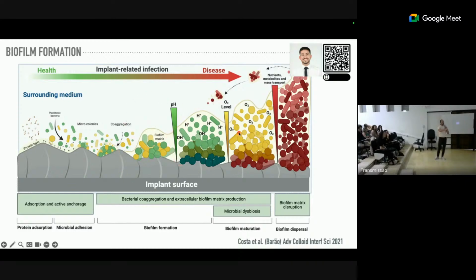In the beginning, this biofilm is more acidic, as we call it. So the pH in the biofilm tends to be low, but as time goes by, the level of oxygen tends to be reduced because the biofilm is very thick. So in the bottom part, especially, we're going to have the survivability of those bacteria that don't like oxygen, like the red complex bacteria that are related to infections, the peri-implant infection or the periodontal infections. And also during this whole process, we have some bacteria that are detaching from this biofilm and forming again this whole process.